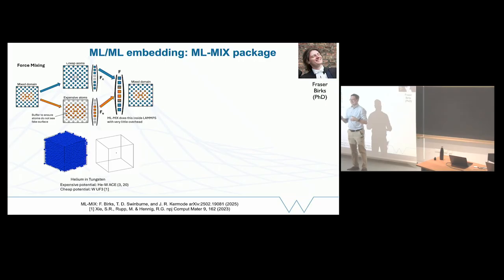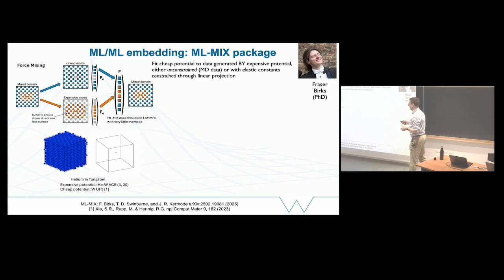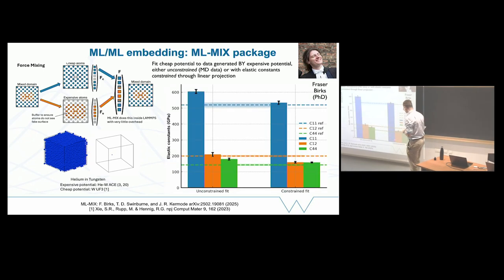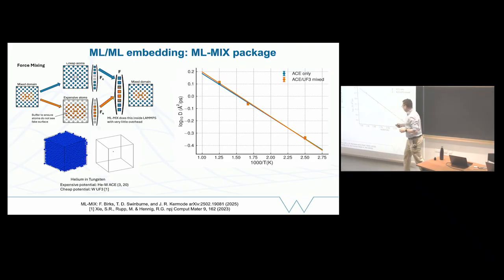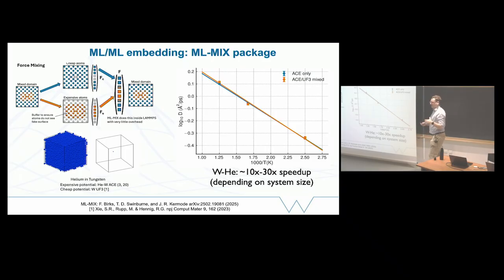So it's like a Stillinger-Weber or one of those potentials, but you machine learn the two-body part and the three-body part. And so it's super fast. It's not very flexible, but it's fine for the bulk. And if we are careful about how we do this so that we match properties between the two regions, for example, we can constrain so that we match the elastic constants between the two potentials quite well. Then if we look at observables like the diffusion constant for the helium moving around in the lattice with the full model and with the mixed model, we get very good agreement. And in this case, we get a big speed up because we're only paying for the high accuracy model where we need it, not everywhere.